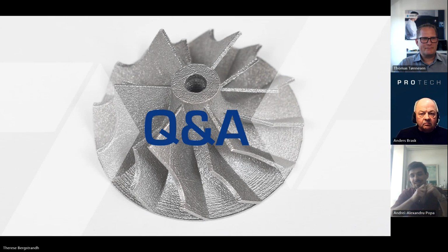So the design considerations are always linked to temperature. Everything that happens inside that chamber while you're printing is a function of temperature. The way you dissipate this heat from the shape down to the build plate is dependent on the supports you generate. So that's actually the art of metal 3D printing, if you ask me. The part itself is cool enough. What do you do with the supports? How can you tailor the supports to structurally support your part, but also dissipate the heat in a meaningful fashion, and then also be able to remove them afterwards? That's where the art really comes in.